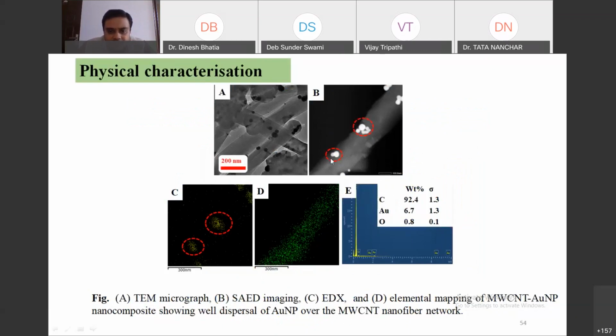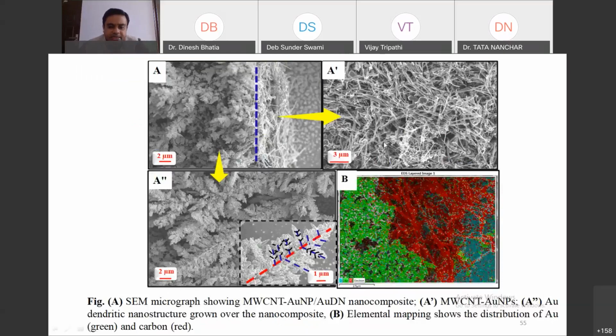Right. So this part and this part is basically the same. The patterning is only different. This is the physical characterization. And after this process, as I said, we have used this as a matrix. You can see the gold nanoparticles. These are the fibers. Over this fiber, you can see a very clear-cut tree-shaped structure has been formed here, which is again a dendritic structure. We have zoomed in this part.